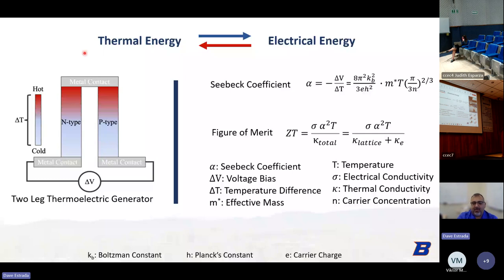And so just a quick recap, if you're not familiar with thermoelectrics, they leverage the Seebeck effect to harvest heat into electrical energy. So you have your N-type and P-type thermoelectric materials connected in series and in parallel with the temperature gradient. And these materials should have a good Seebeck coefficient for your target operating temperature. And that Seebeck coefficient, the details are here, but it's the change in voltage over the temperature gradient. And this goes into the figure of merit in the numerator, where the numerator is known as the power factor. And so that includes the electrical conductivity, the Seebeck coefficient squared, and this is over the thermal conductivity, which includes the lattice contribution from phonons, as well as the electronic contribution from the electrons.